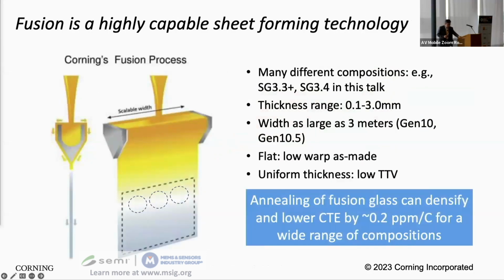So we decided to use a glass made by fusion and cut wafers out of a big sheet. And we want to leverage a unique characteristic of a fusion type of glass. When you draw a sheet in air and you draw it fast, the glass actually cools down very quickly, which leads to a quasi-static kind of property. The glass isn't in a thermodynamically stable state. So this gives you a CTE that you can tweak through annealing.